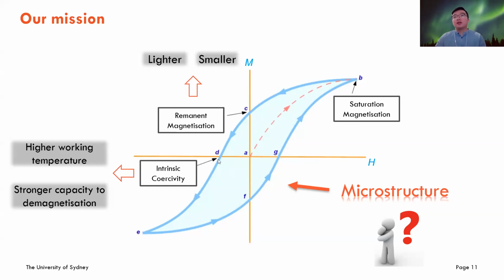The other important point is point D, which is called the coercivity. That represents how strongly the magnet can resist the demagnetization field. If the coercivity is higher, then the magnet can work in much more severe conditions, such as higher or even lower working temperatures. So what we would like to do is to make this point higher, to make D a bit further from the origin. And to do that, we can't avoid one point, which is to tune or tailor the microstructure of the magnets, because especially the coercivity is quite relevant to the microstructure.